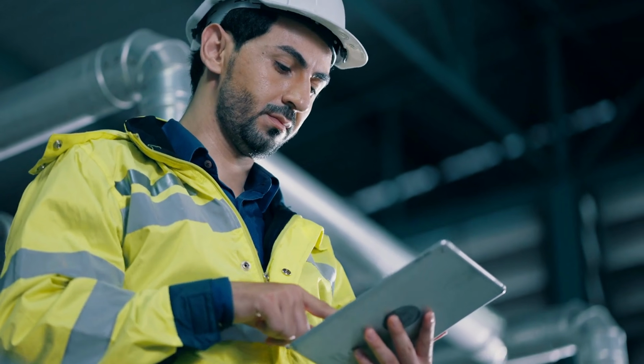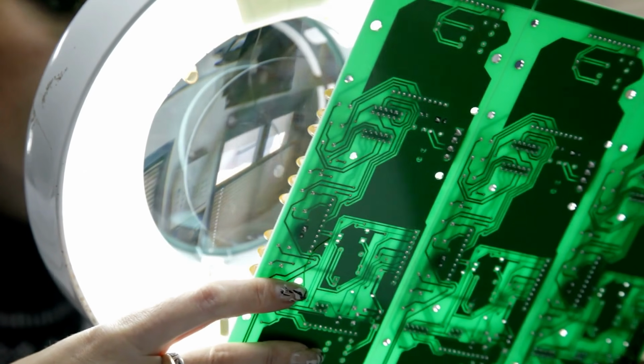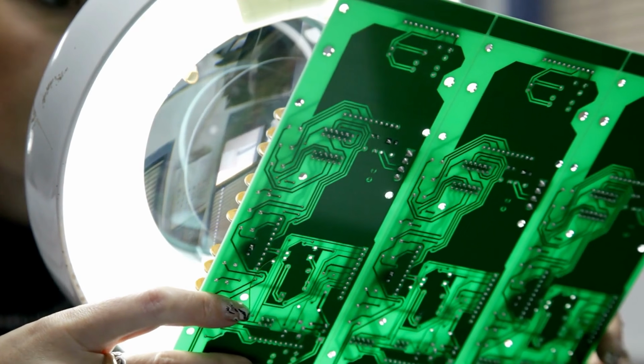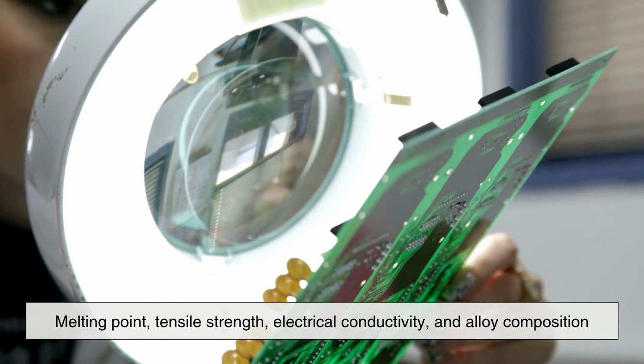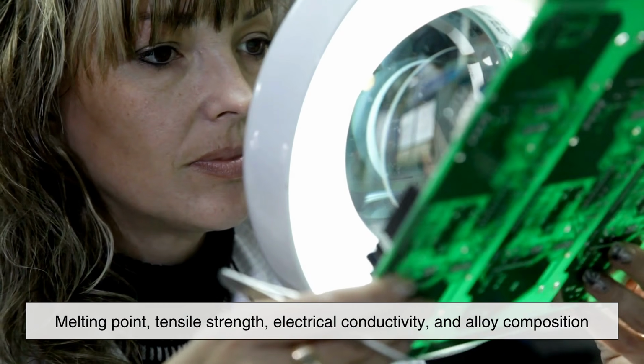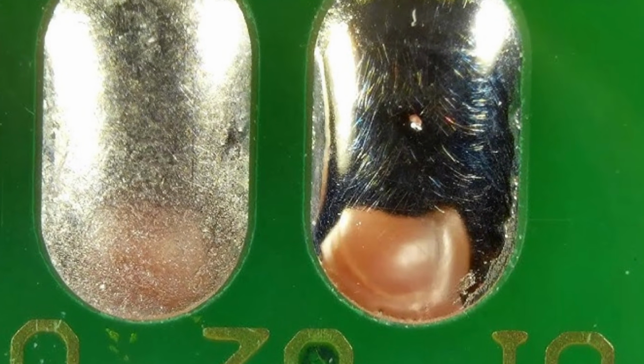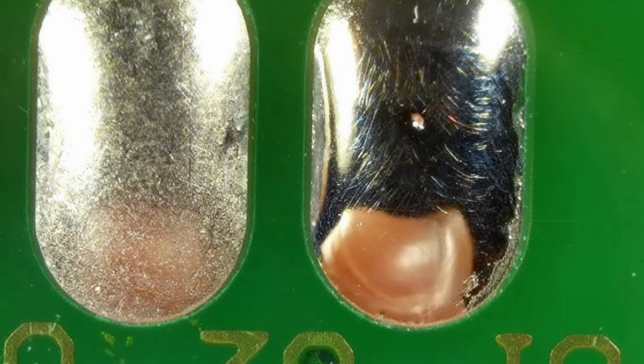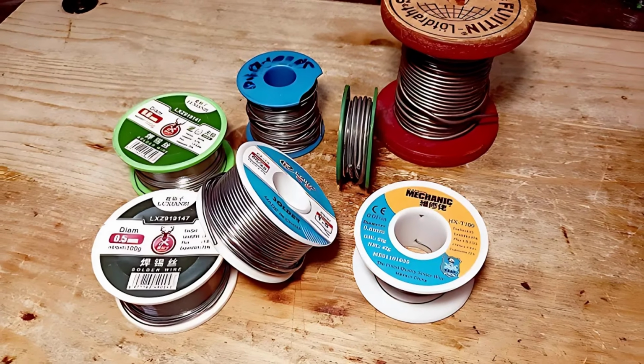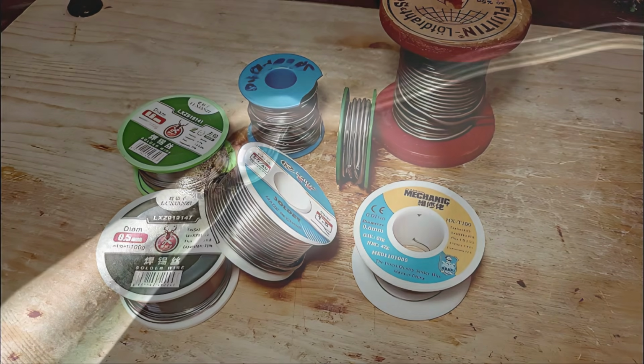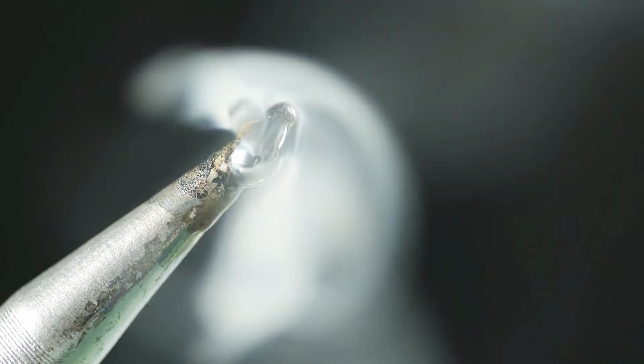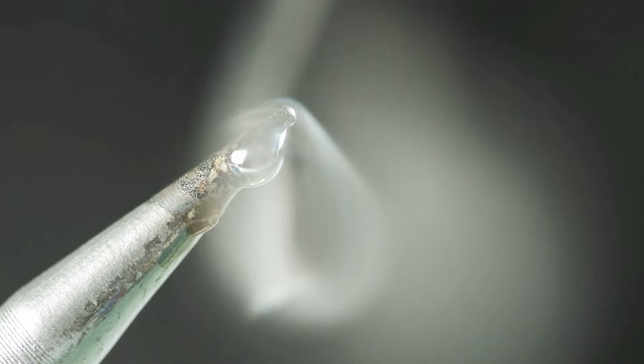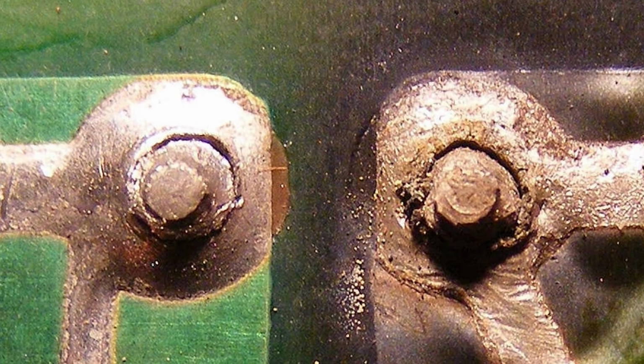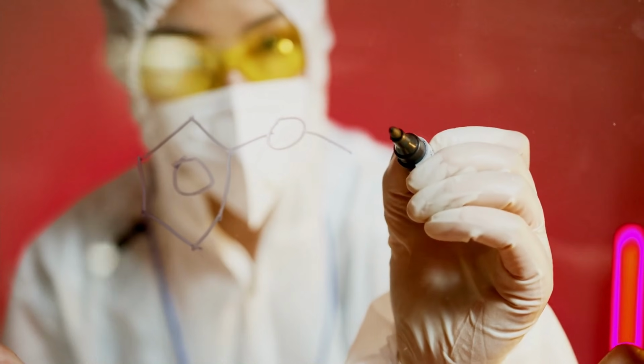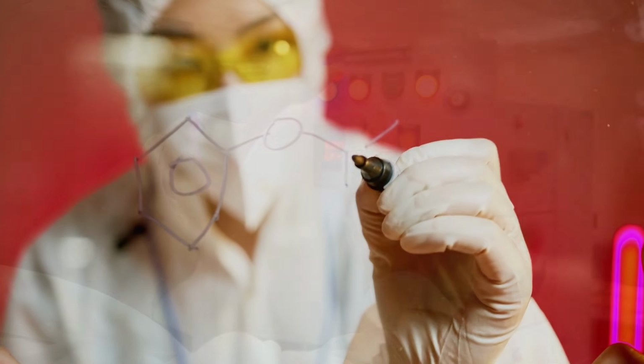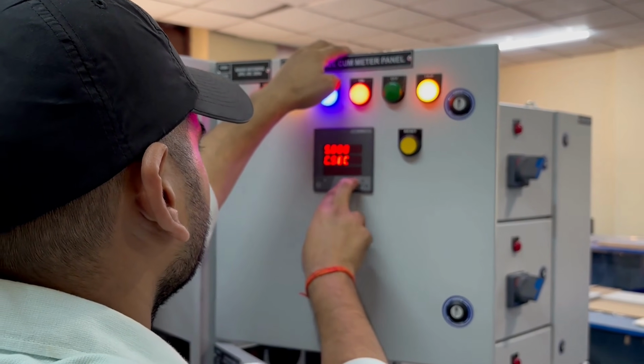Quality control is a huge part of the solder-making process. Manufacturers constantly test their solder for things like melting point, tensile strength, electrical conductivity, and alloy composition. Even slight deviations in the metal ratio can drastically affect performance, for instance, making solder brittle or too soft, affecting how it behaves under stress or heat. Impurities like iron, zinc, or aluminum can make the solder flow poorly or cause it to oxidize rapidly, leading to bad joints. That's why rigorous testing, including chemical analysis and performance evaluation, is essential before the solder is cleared for commercial use.